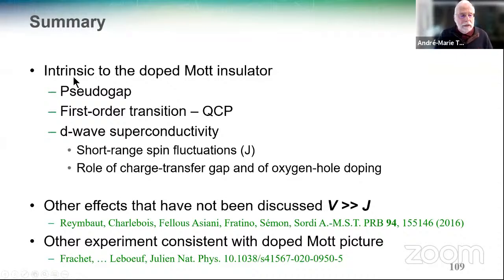So I think I showed you that what's intrinsic to the doped Mott insulator is that there's a pseudogap. There are first order transitions that you see at half filling, the Mott transition. And then at finite doping, there is a Sordi transition that's continuously connected. That can give rise to a quantum critical point if you go to large values of U. There's d-wave superconductivity that's mediated by short-range spin fluctuations.